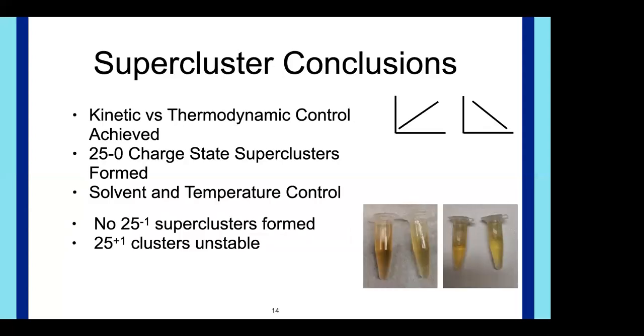So, some conclusions based on the experimental work so far. We've achieved kinetic and thermodynamic growth system control based on the different timescales that were used for the temperature quenching here. This was done just with 25 in the 0 charge state superclusters. Shown a little bit of solvent control over the thermodynamically stable supercluster size in solution. The more anti-solvent you have, the larger the supercluster formed. And also temperature control based on the kinetic and thermodynamic systems.